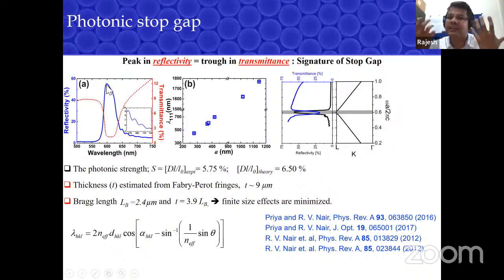So you say that my sample has a direction dependent band gap because you are only looking at one direction. And if you change the angle of incidence, this wavelength will shift because it is an interference process. We made quite a lot of these samples, I think around 6 or 7 samples. You can see that if the lattice constant, which is basically the sphere diameter, is close to 300, you get a band gap here. And if you increase the lattice constant, the band gap wavelength also increases. So if you want it at 500 nanometer, you need to use this lattice constant. If you want it at 1800 nanometer, you have to use this lattice constant. It's scalable because it's an interference process.